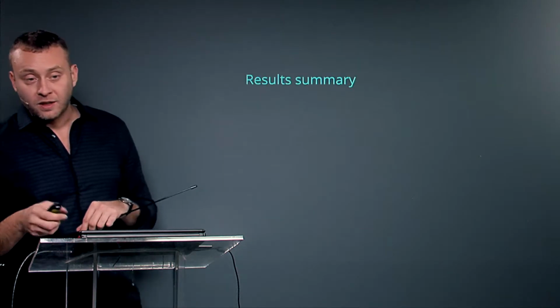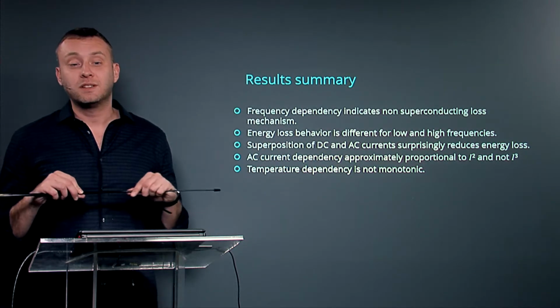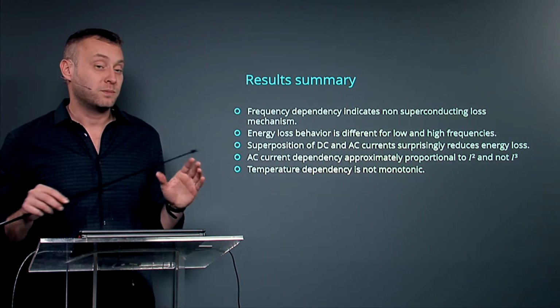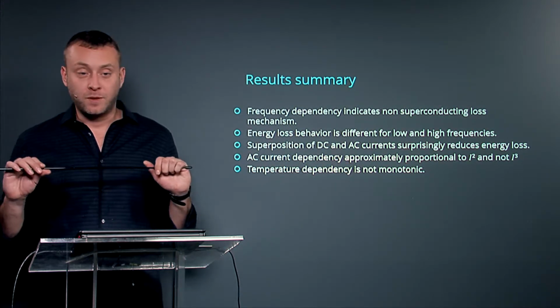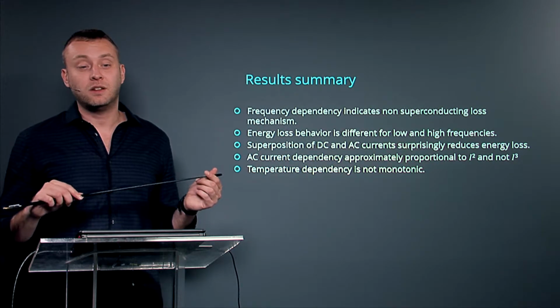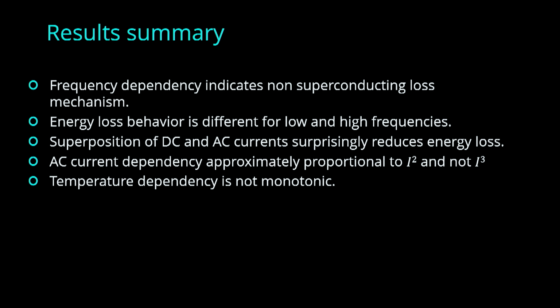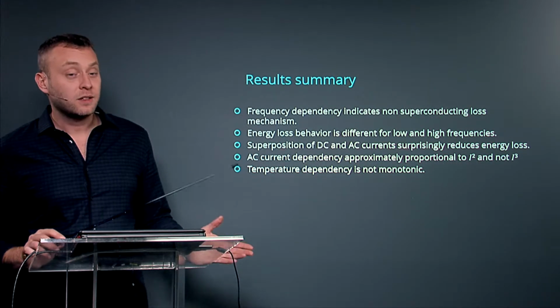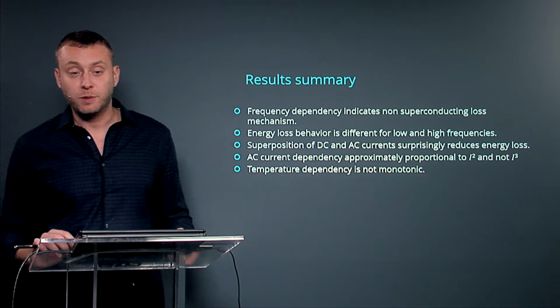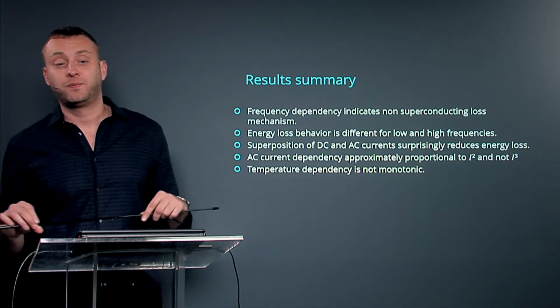So what actually do we have here in this experiment? We see that the frequency dependency indicates a non-superconducting loss mechanism, because we expected that the energy loss does not depend on frequency, and we see it depends very much. Energy loss behavior is different for low and high frequencies. We see the crossover from 2 different regimes in the energy loss plots, and surprisingly, the DC and AC current superposition reduces the energy loss.